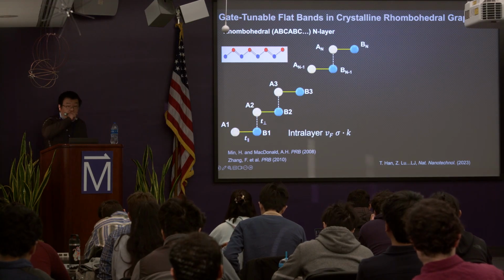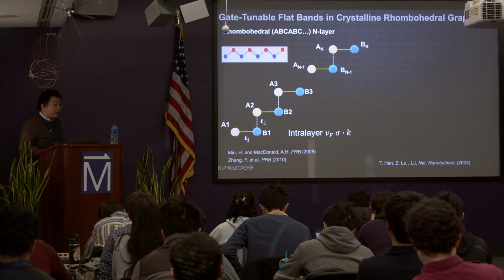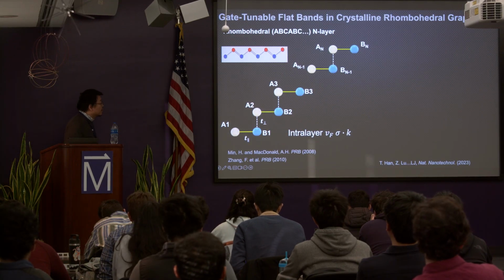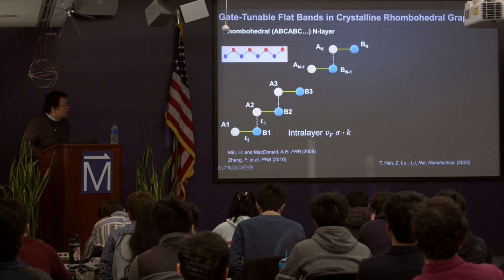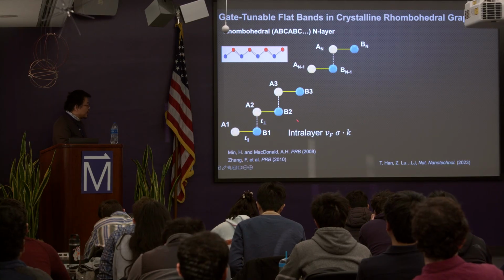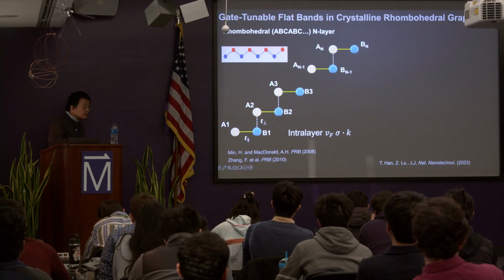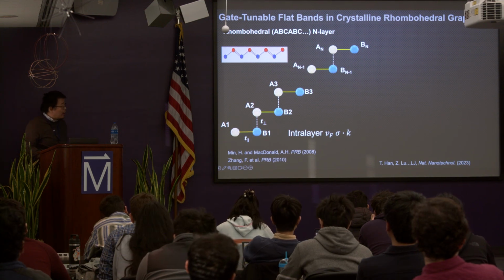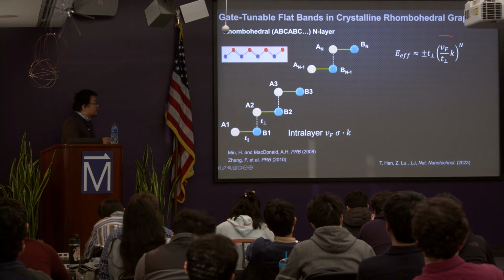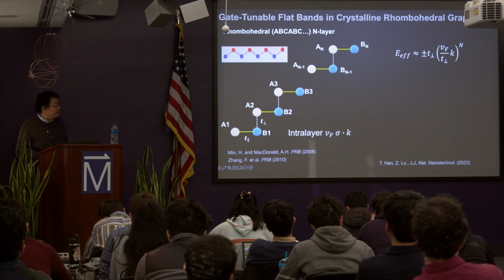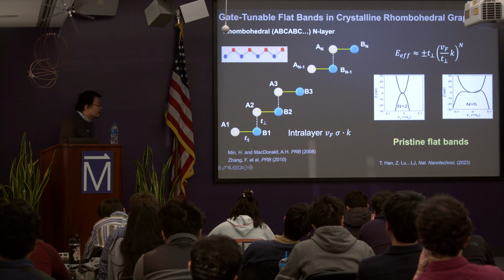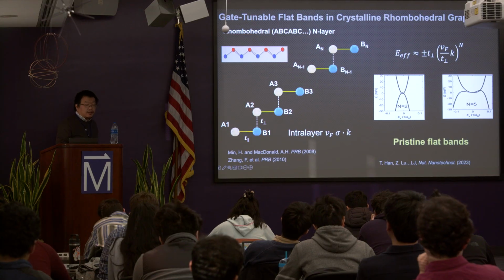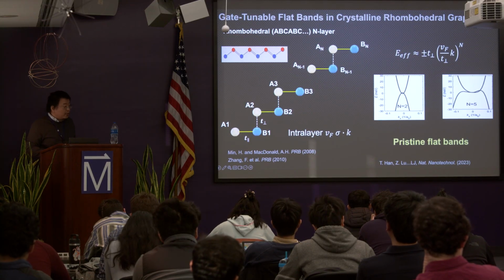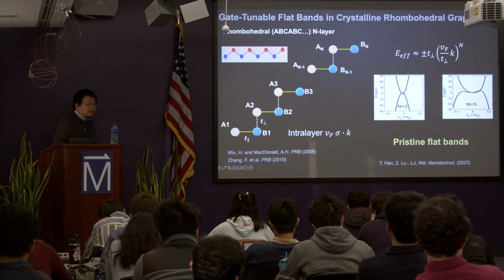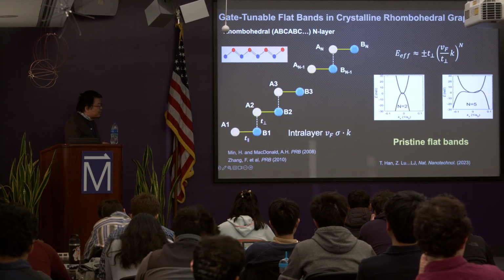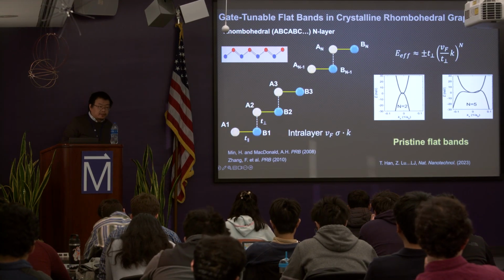Starting from the band structure of rhombohedral graphene, I think Andrea already gave a very clear explanation. It's basically just an SSH model. The low energy band structure is dominated by the two corner sites, A1 and Bn, and the dispersion follows k to the nth power. Which means that if you have thicker and thicker graphite, you get a flatter and flatter band structure at low energy. So this gives you more or less pristine flat bands, although it doesn't really look perfectly flat, but it's much better than single layer and bilayer.